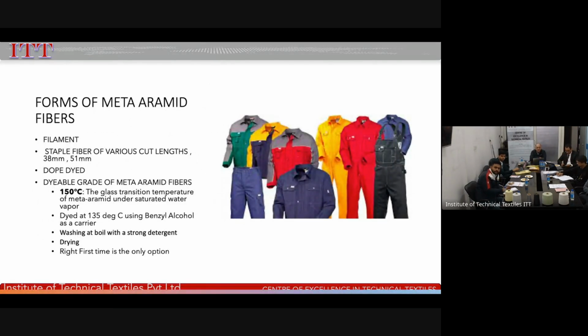These fibers are available in the filament form. Then they are also available in the staple form, and these staple fibers are used for blending with others. Now this is also available as a dope dye, and there are also dyeable grades of meta-aramid fibers. These meta-aramid fibers have a glass transition of 150 degrees centigrade. They can be dyed using benzyl alcohol as carrier at 135 degrees centigrade.